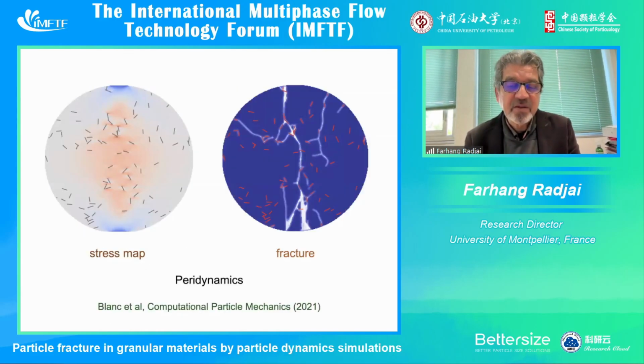We're using peridynamics. I will not go into details of this method, but in one sentence, peridynamics is discretization of the material on a grid using the integral form of the equations of motion. So it is a non-local approach. Here you see one example of a spherical particle, but with defects inside. These defects that you can see here as small segments can be distributed inside the material and subjected here, for example, to diametral compression.